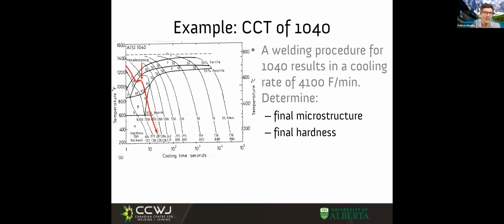Somebody suggests 9, but no. So these diagrams make a number of hypotheses, some of which are not really true, but let's take the lie and move on, right? The guy says 8% primary ferrite. The truth is sometimes the primary ferrite keeps transforming too, but let's not worry about that. Let's say that it gets locked at 8%. Any new ferrite is going to come from the pearlite, and it's not primary ferrite anymore and looks so different.